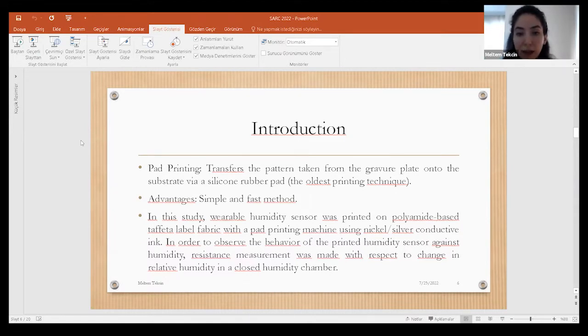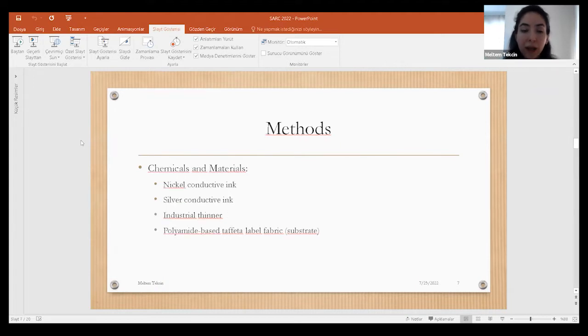In the study, a wearable humidity sensor was printed on polyamide-based label fabric with a pad printing machine using nickel and silver conducting ink. In order to observe the behavior of the printed humidity sensor against humidity, resistance measurements were made with respect to change in relative humidity in a closed humidity chamber.